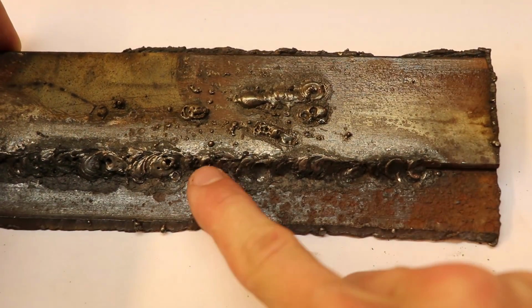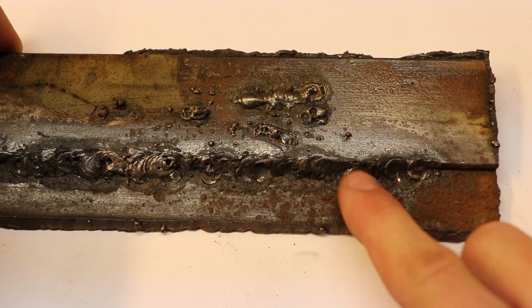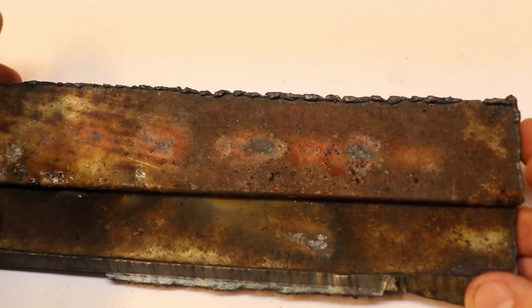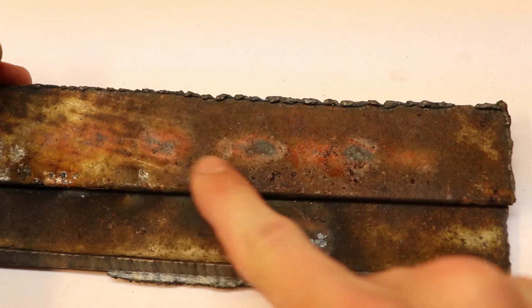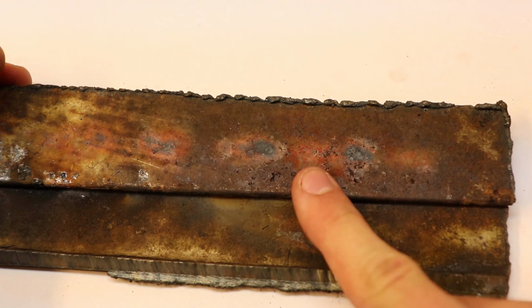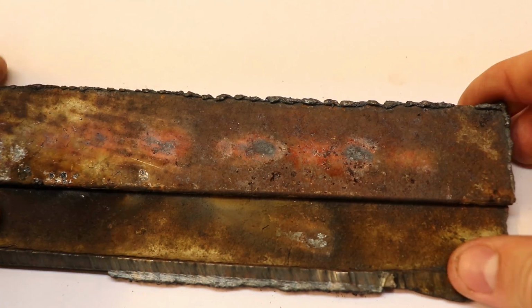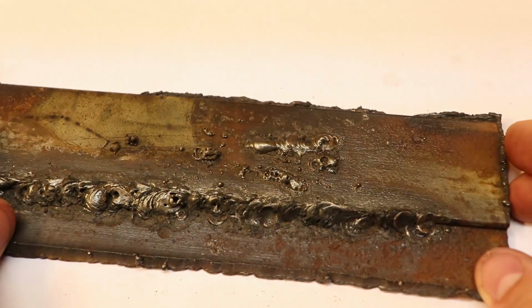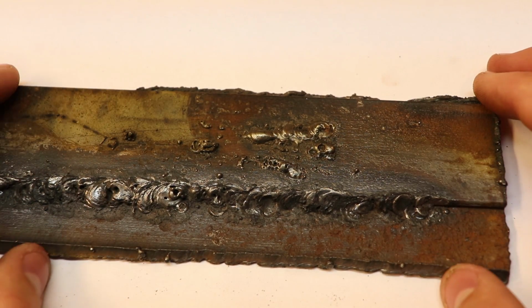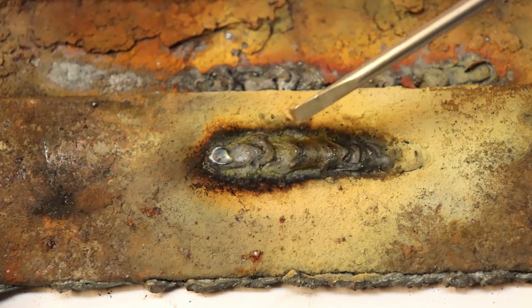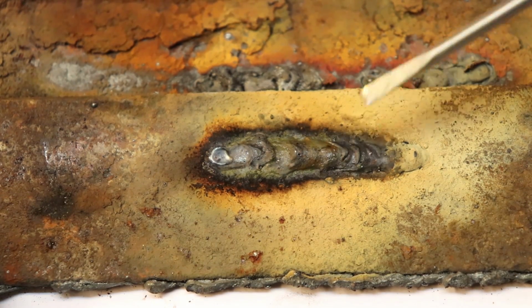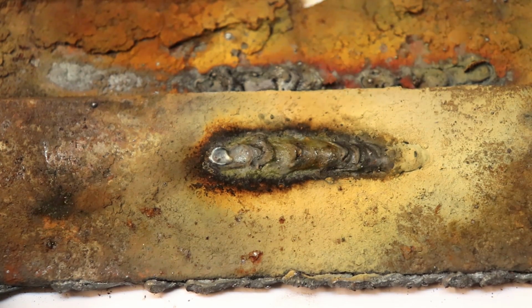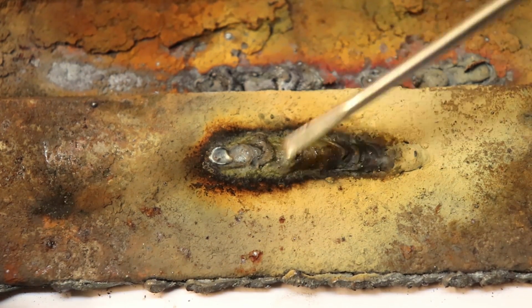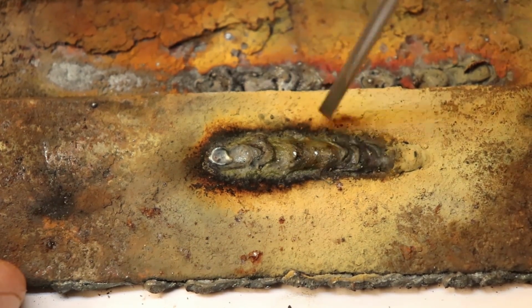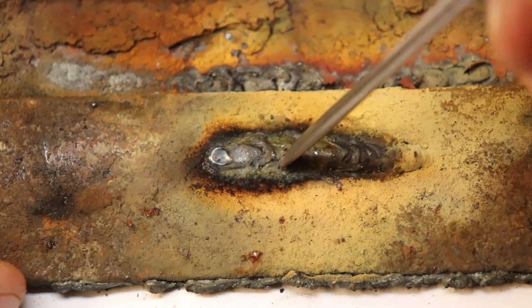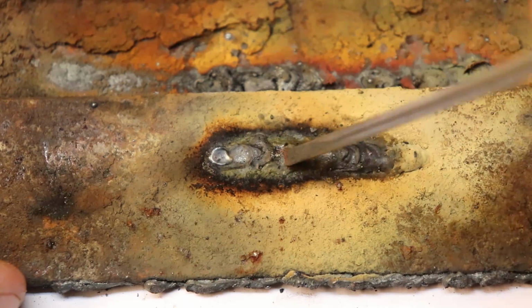But I want to point out, at least with these two plates, where I got good penetration, you can easily see in the back of the plate some discoloration. And these rods do penetrate into the metal, so it's actually way better than before, way better than the first batch of welding rods I did. All right, now if I get lucky and I start scraping this, maybe some slag will fall off, and basically I can show you that there is some slag on this. All right, yeah, there we go.